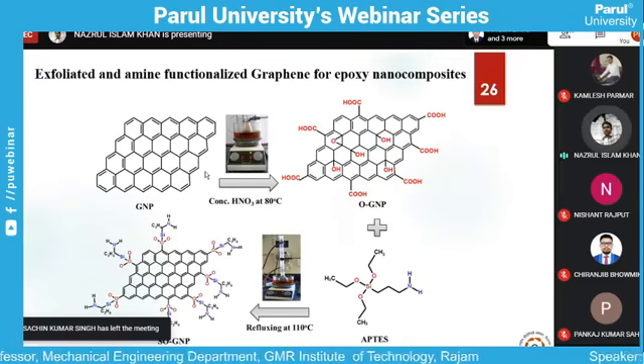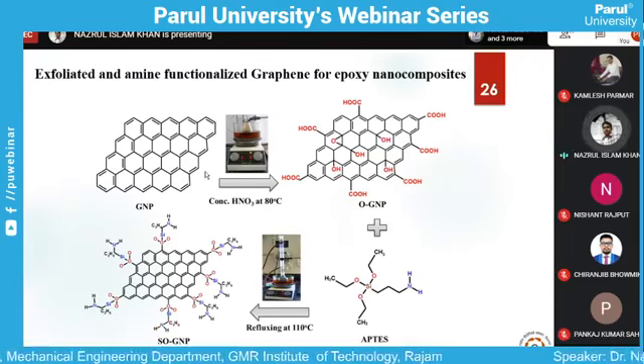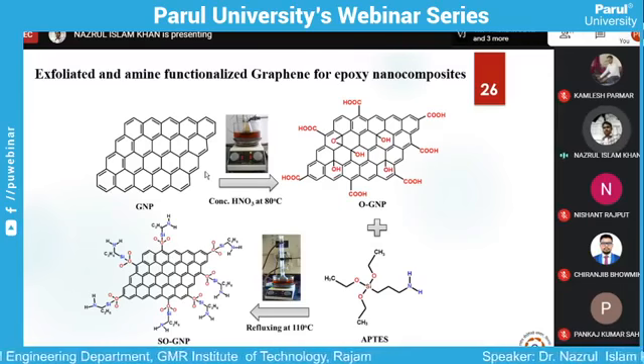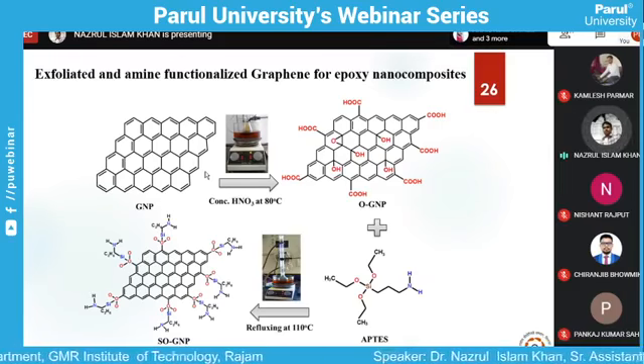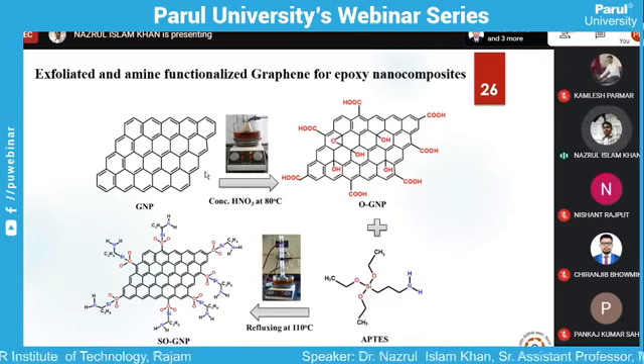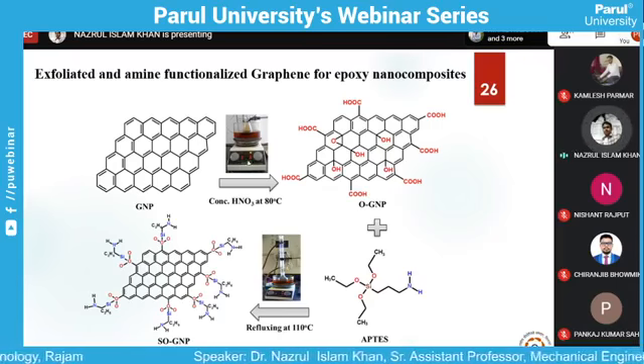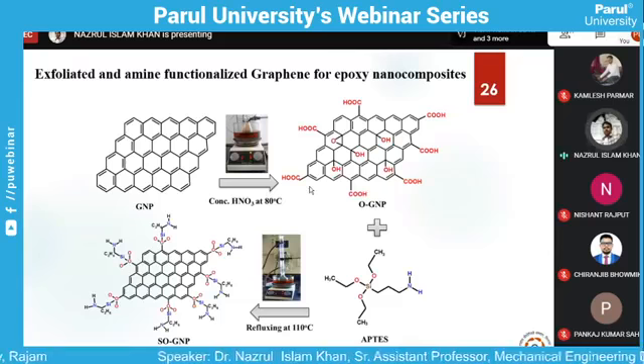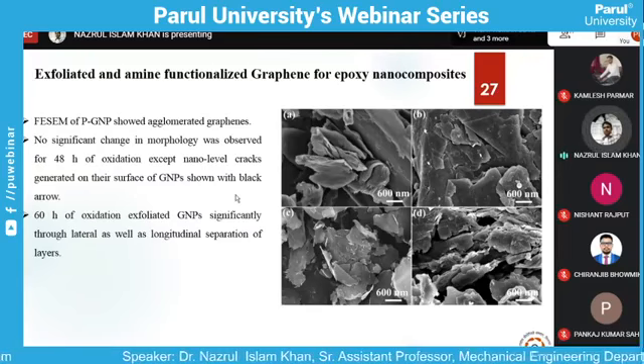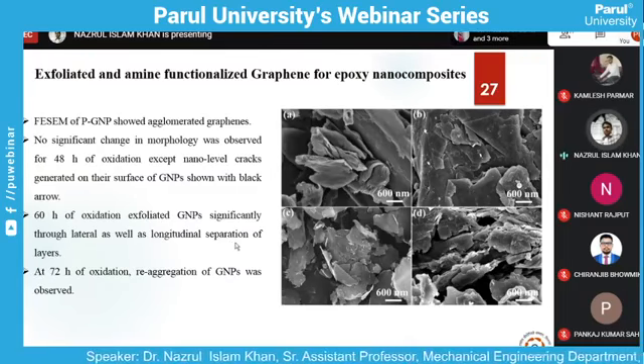Now coming back to the example of graphene, although we have taken the graphite nanoparticle, those are small particles, but the exploration of graphite nanoparticle was very difficult. But nowadays you can see there is a huge application of graphene. So here we have taken some graphene nanoplatelets and we tried to modify their surface using different oxidation time, different oxidation temperature, and we optimized that. And here we found a very interesting point.